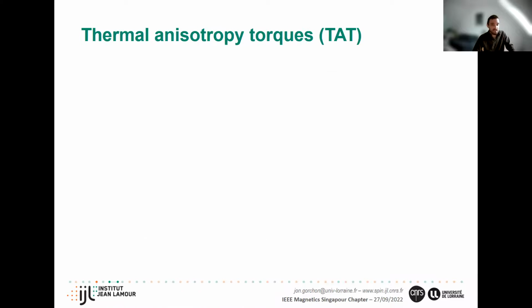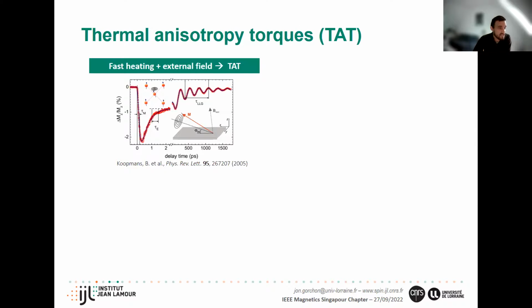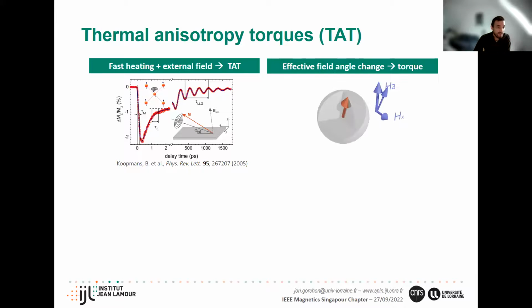There's one last element I didn't talk about here, which is that when you heat a magnet very fast and you have an in-plane field, you can get what we call a thermal anisotropy torque. This has been used, for example, to characterize the damping and the anisotropy in a magnet by doing an ultra-fast optical experiment. The reason is that if you're starting in this configuration, where you have the anisotropy field pointing up and an external field pointing in plane, when you heat it up, the anisotropy field drops.